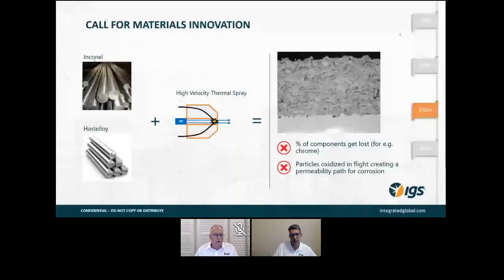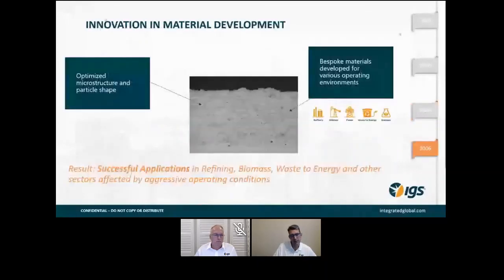So this discovery led to another step change, I would say the next step change, in terms of the technology that IGS developed. And this is where we got into the world of alloy modification. If you have a picture in your mind of what that last micrograph looked like, the one on this page has a lot less gray phase in it, so much lower oxides. In most of the coatings that we apply now with our next generation materials, those oxide percentages are usually below 1%.